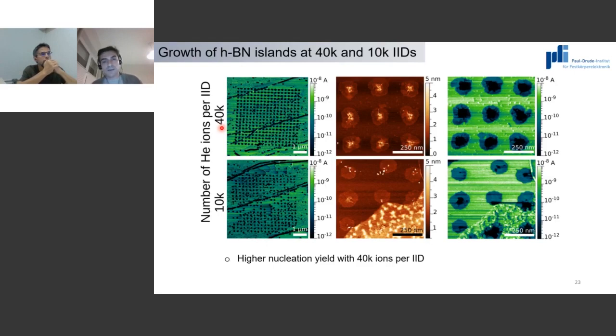We have a nano-hole there. It's not like a single vacancy. And that's when we grow HBN, but it's more disordered, and we still have this out-of-plane growth going on. While if we use a lower dose, where we expect that smaller defects are being formed, but again, we still don't know what defect it is, but we do see an influence in the growth. By growing HBN with the very same conditions, we do have a preferential monolayer formation, so this vertical growth in the center decreased quite a lot.